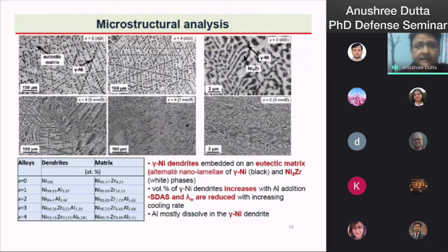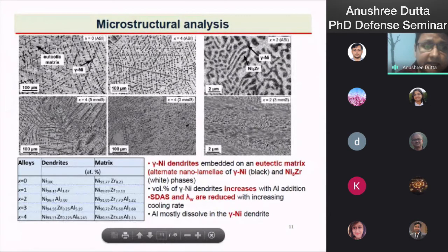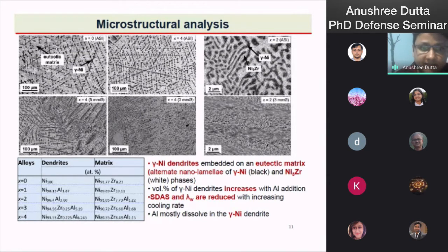Scanning electron microscopy analysis of the microstructure shows the gamma nickel dendritic phase embedded in a brighter eutectic matrix, shown here for x equals 0, whereas the volume percentage of the gamma nickel dendritic phase increases with aluminum percentage. We can observe that the percentage of the darker dendritic phase increases at x equals 4 alloy. The refinement of the gamma nickel dendritic phase can be observed in 5 millimeter and 3 millimeter diameter rods. In the higher resolution image, we can see that this brighter eutectic matrix is actually composed of two phases, gamma nickel and Ni5Zr phase. The refinement of the microstructure has been observed in the 3 millimeter diameter rod.